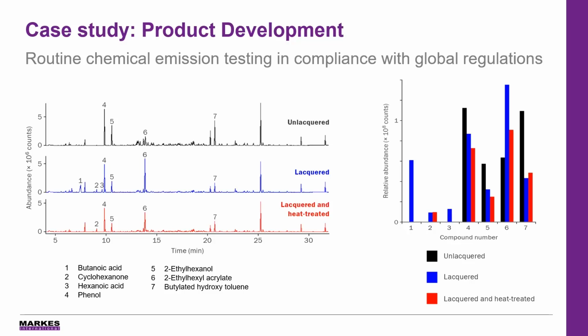So in the first trace, we can see that we've got quite high levels of phenol and also BHT. And these are 2 compounds that are regulated within the relevant construction regulations. So the sample was then lacquered, and during that lacquering process, the emission of phenol and BHT were both reduced. However, that lacquer did add additional concentrations of butanoic acid and also